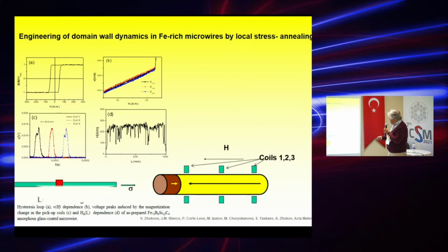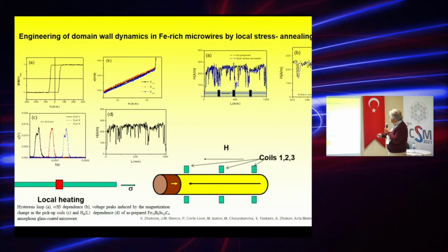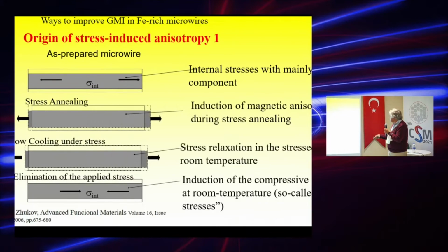Now if we apply local annealing, for example, we apply stress and heat the sample in one place, we can create defects, which are shown here. This is the profile of the nucleation field. In this place, we can inject the domain wall on application of an external magnetic field, and now the magnetization changes. You can compare these peaks now. The first and second peaks appear simultaneously, meaning that it is the same sample, and now domain walls nucleate in a different place, and then you can observe propagation of several domain walls. So we have a kind of artificial defect, or a more soft magnetic region, in our material. This is another possibility to use the stress induced anisotropy for different applications.